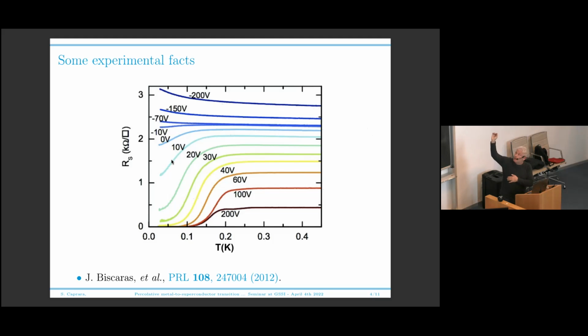What was striking of all these curves is that in a situation like this, you see that there is a superconducting transition nonetheless. You go from a metal to a superconductor. But look at this curve here. You have a metal, you have a huge fraction of your sample which must be superconducting because your resistance drops quite abruptly. But then at low temperature, you reach a state with a finite resistance. This is not a superconductor. The resistance of your two-dimensional electron gas is finite down to very low temperature. Nonetheless, there must be a significant fraction of your system that has become superconducting. At least this is our interpretation of this curve.